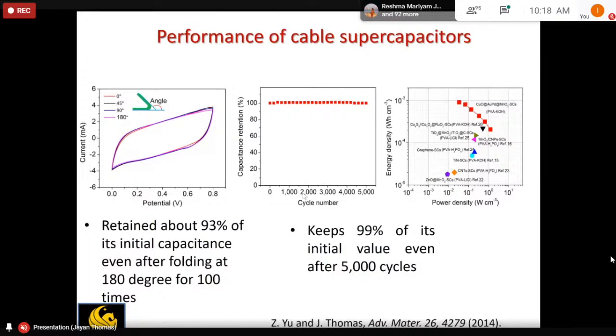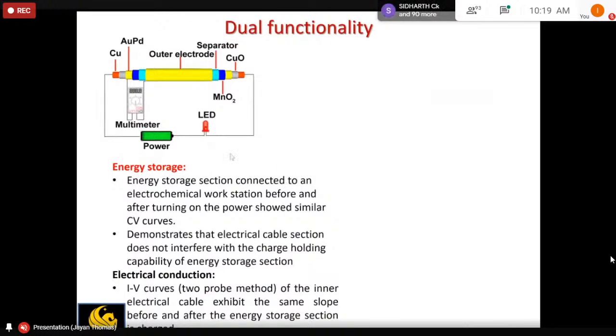And here, this is just to show the cycle life. Even after cycling up to 5,000 cycles, you can see that the capacitance retention, or the energy retention, is almost 100%, which means that this is a very stable energy storage device, and it showed reasonably good energy harvesting and storing properties. And then we demonstrated dual functionality for this cable, that is, energy transmission and energy storage.